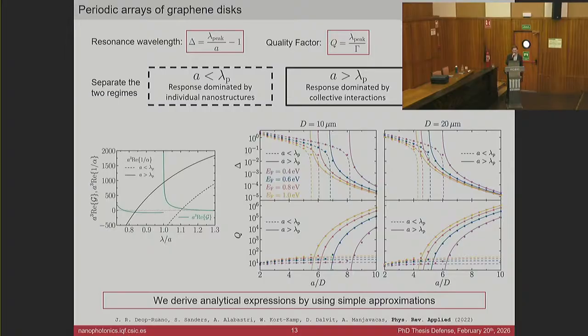Yes, that is a really good point. As you said, in principle, in our calculations, the quality factor, if you get increasingly large lattice sum, can grow unbounded. However, this is in our model. This is in the theory where we have a perfectly periodic array that is also infinite because it's periodic. However, if you go to a real system, the interaction is not going to be infinite. The first reason is because the system is actually finite, and this is going to limit how much interaction you are going to have between your nanostructures.